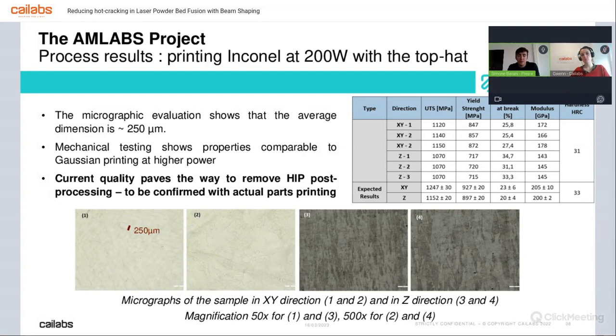But this decrease in mechanical properties, correlated to the fact that we have no hot cracking and correlated to a small laser spot, will let us arrive to the consideration that what we have done to the system is to give an energy that is lower to the point. So we have formed a less quantity of gamma prime phases in this manufacturing production that have a lower strengthening effect on the material, and so have reached slightly lower mechanical properties, but also no hot cracking.